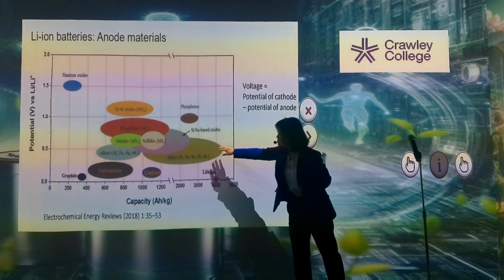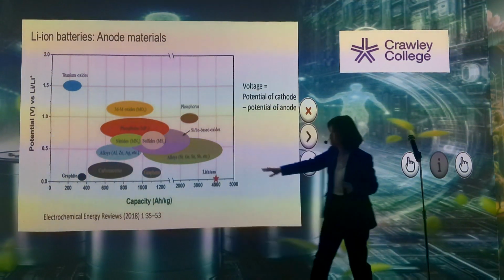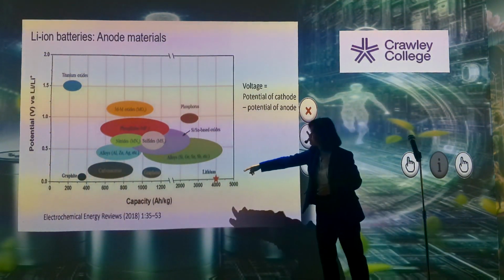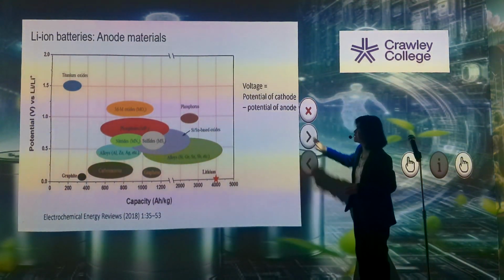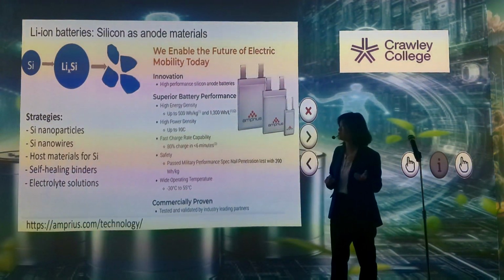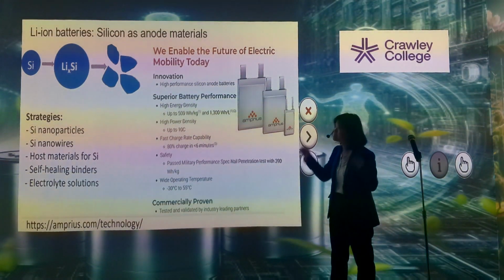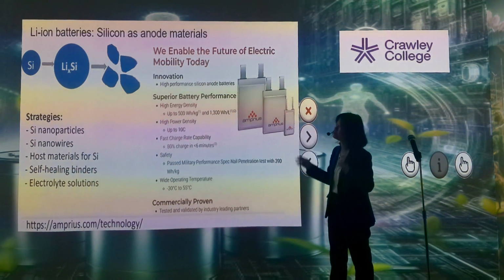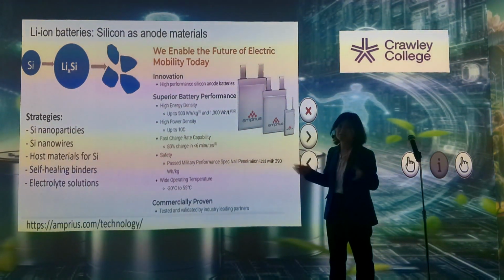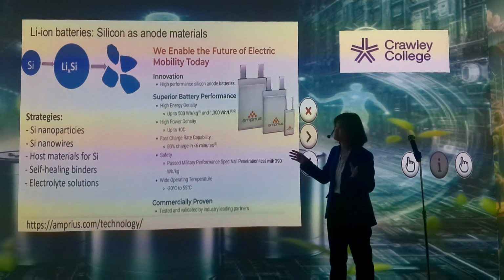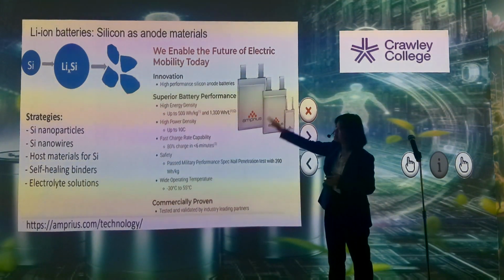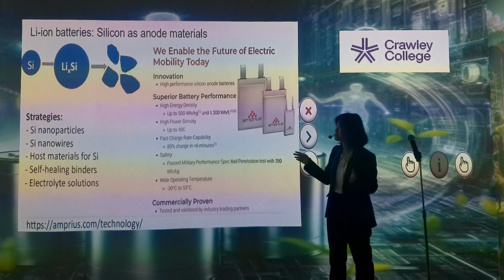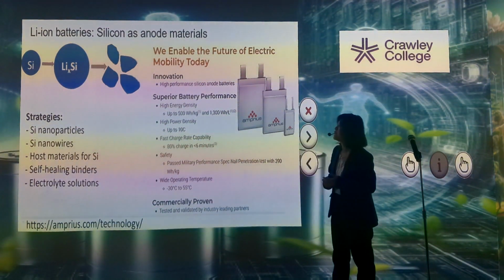Now, if you want a higher storage capacity, then you go for the alloy type. Typically, silicon and tin have been used, and also lithium would be the ideal candidate, and I will talk about them. Now, the problem with alloy type material like silicon or tin is when they intercalate lithium, they have huge volume expansion. For silicon, that's 400%. And that huge volume expansion will cause cracks and therefore particle breakdown and therefore loss of contact. So performance decays, and there have been different strategies to improve this, trying to make silicon into nanoparticles, nanowires, or use a host material, and also maybe use self-healing binders and some solutions that try to repair the material.